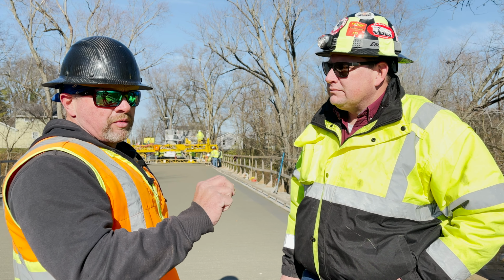We said, well, we want to change the ingredients out to make it more user-friendly, but we don't want to change the application. We want to keep it as low permeability as possible to prevent chloride intrusion. If we do have chloride intrusion, we want to prevent that from spreading, which is what I went through earlier with our bonding agent that's also a corrosion inhibitor. So we've tried to cover our bases on that.